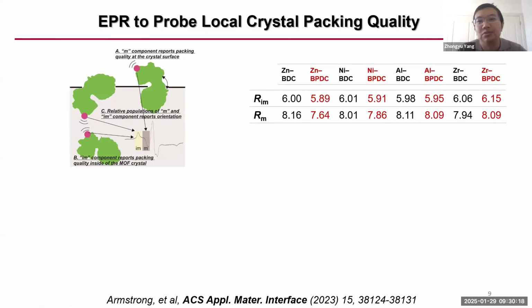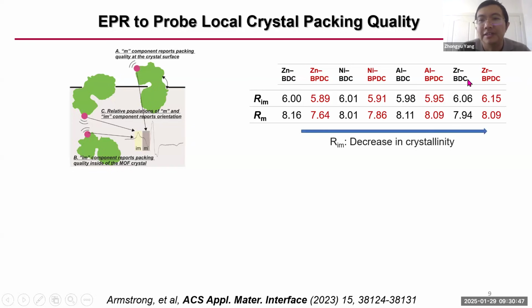So by doing that, we found, I know I showed you 10 MOFs, but there's a copper BPDC, copper BDC MOF. The copper signal messes up the nitroxide signal. So we're still analyzing those data. But with these 8 MOFs, we already found that, if you remember the previous slide, right, zinc BPDC, this is higher crystallization and this side is lower crystallization. So as we decrease in crystallization, the immobile component of the R value is decreased.